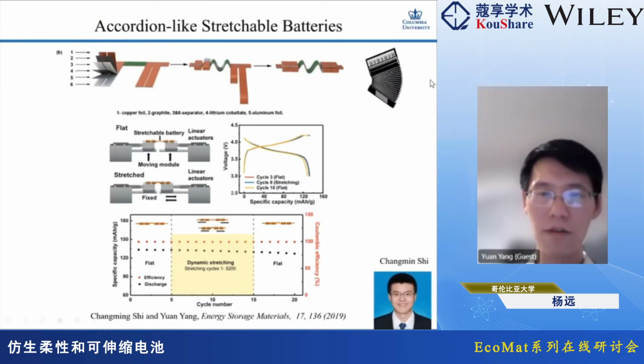We can also modify the spine-like structure to make it stretchable. Basically, in the interconnection part, we can make a zigzag, so they can actually be stretched. We also show that during stretching, 5,000 times of stretching over 10 cycles, the capacity is pretty stable.